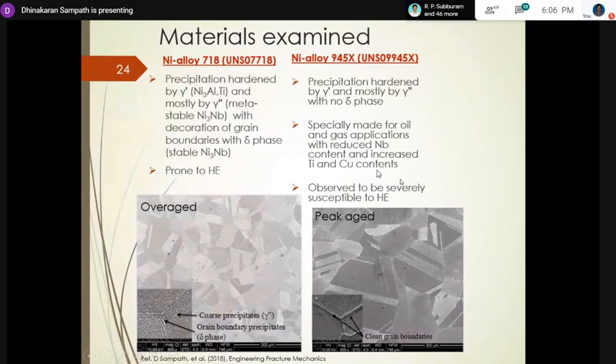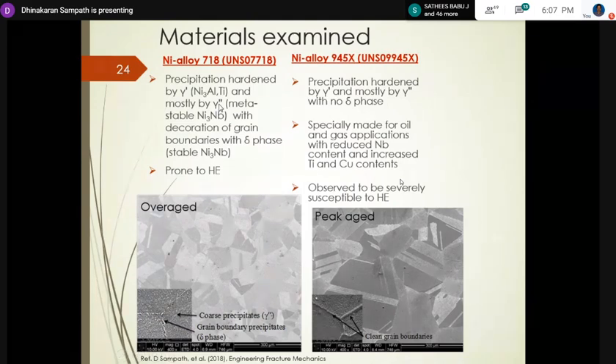Before that, what is precipitation hardening? That is a strengthening mechanism. They rely on fine precipitates like gamma prime and gamma double prime. Moving dislocations cause the plasticity, but these precipitates stop them. The amount of load required to cut the precipitate or just form a loop, they call Orowan looping, means we need to apply more stress, more load, to get past the precipitate. Thereby it increases the strength of the material.